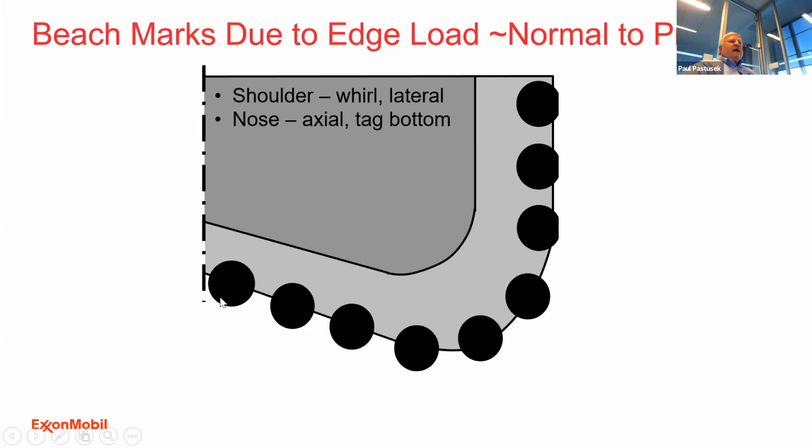And it happens so rarely now, I can't really rely on it. I can have very severe stick slip and they just don't show up. And why is that? It's because the cutters are tougher than they've ever been. So I don't show that as a diagnostic anymore. In terms of one, it's not often seen. And number two, I can have severe stick slip and not see this damage. So it doesn't become a really good diagnostic for stick slip. Digital data, can you look at my torque variation, is a much better diagnostic.